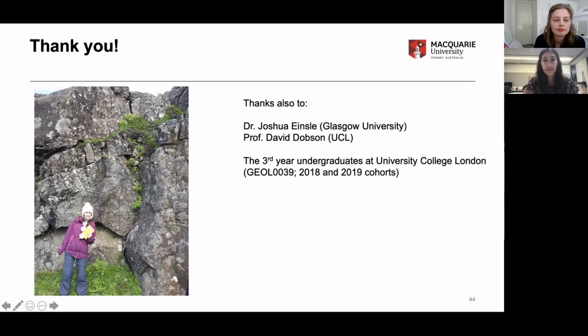Thanks, that's a great question. So the EBSD, actually, we tried this on my samples, and those of you that work with experimental samples will already have appreciation for the silica colloidal polishing that you need to do in order to get very good EBSD data, which is really difficult. And I already had a hardness contrast between my spinel grains and the orthopyroxene background. And actually what happened during the polishing process was I gouged out a lot of the material. So I wasn't able to actually do the EBSD.